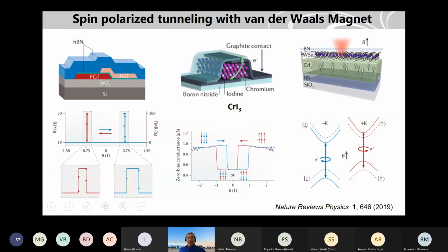And again, chromium iodide is an antiferromagnet, as you know, if it has different layers. Here it's a bilayer structure, and because it's an insulator, you can do a tunneling experiment through this. So it has two graphite electrodes, and they are looking for tunneling transport through chromium iodide. You can see the change in the conductance with magnetic field when you align different layers differently, whether they are all up or all down, or anti-parallel. Quite interesting.